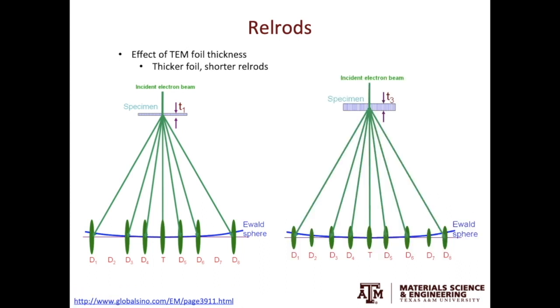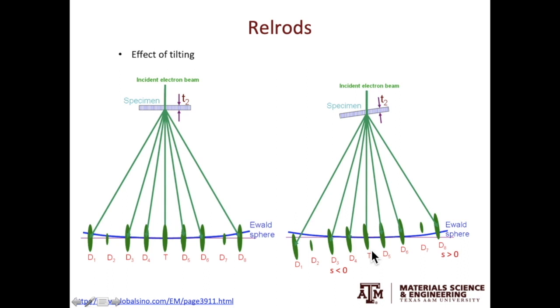Now, let's think about a few scenarios. The first is: what if we change the TEM specimen thickness? In real space, if the specimen is thicker, in reciprocal space the relrods will be shorter. What this tells us is that as we move to larger G vectors, the intensity of the spots can diminish a lot faster in thicker specimens.